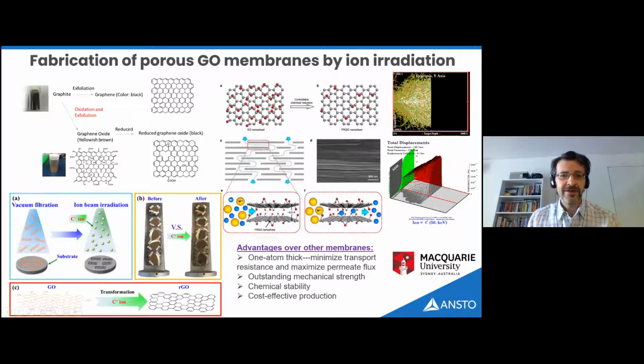So we used again low energy ion beam in order to implant or irradiate very thin graphene oxygenated membranes. And by irradiating them, we produced defects, simple defects like vacancies or complex defects. But the most important thing is that by creating these defects, we actually started creating pores through which ions and atoms can permeate. And by increasing the number of these pores, we can actually tune or modulate the permeability of our membranes.